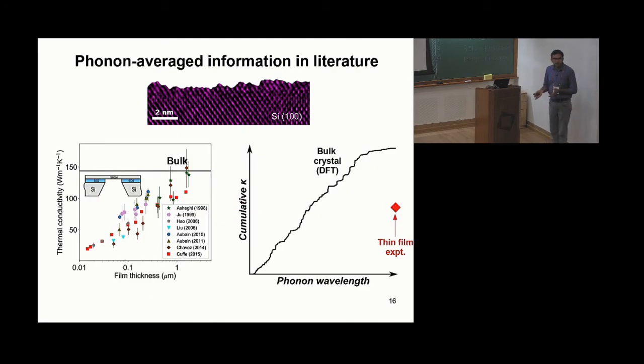This kind of experiment has been attempted in the past from a different angle. They systematically reduced the thickness of the silicon membrane. By reducing the thickness, you increase the surface area to volume ratio, which means you increase the rate at which phonons scatter at a rough surface. More scattering means smaller thermal conductivity, which is what you see in this figure.